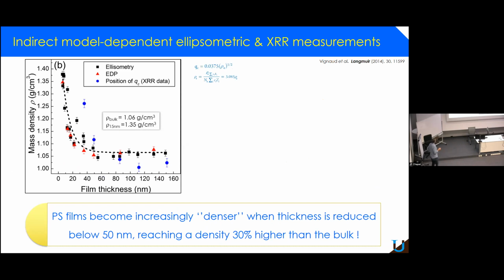In that experiment, this is a graph showing all the measurements that were done, the ellipsometric measurements translated into mass density using the Clausius-Mossotti relationship, but also some measurements made using the electron density profile that you can extract from an X-ray reflectivity curve. Obviously, this is model dependent, but still. And also, in some cases, when the film is not that small, you can extract directly the electronic density of the film from the critical wave vector for the polystyrene. And here you can see that, from that experiment, it's obvious that the mass density is somehow increasing quite a lot for polystyrene when the thickness is reduced.